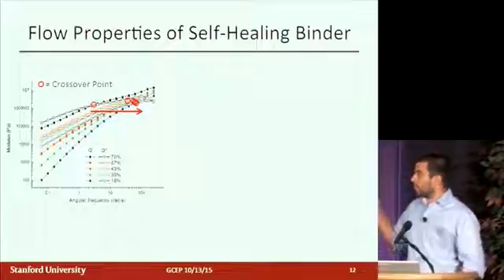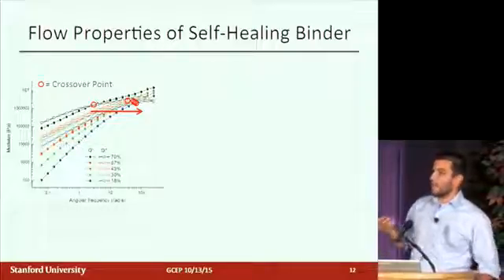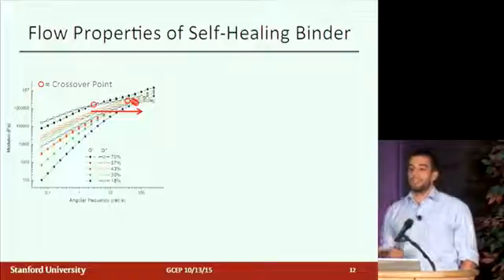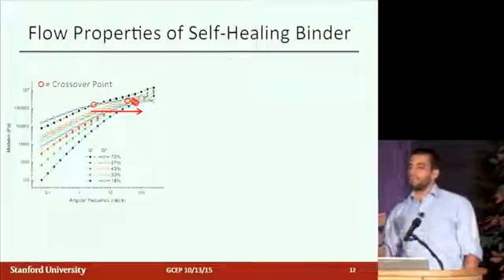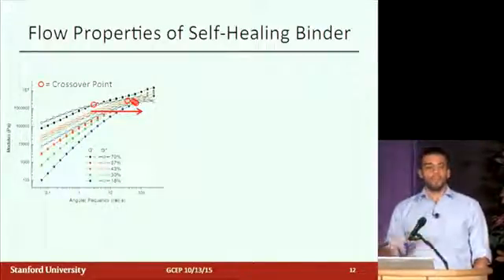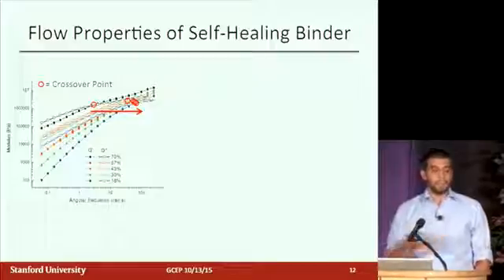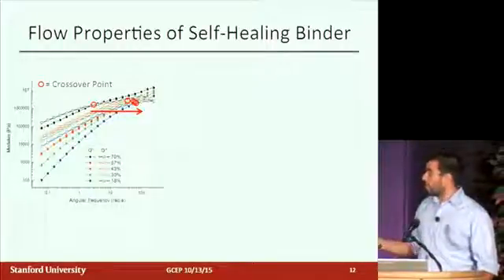And what you can do from those times is calculate a relaxation time, a characteristic time that the material behaves more like a liquid or more like a solid. And we use that to quantify these different binders that I've made and then compare them.